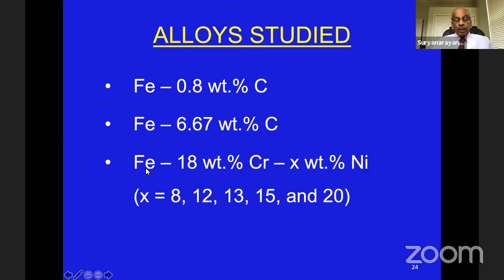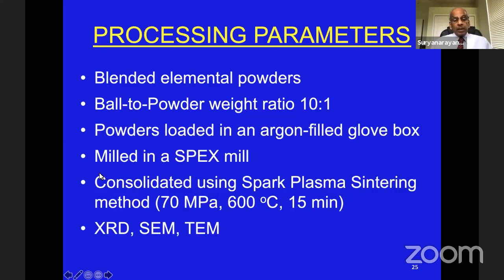And the third one is the austenitic stainless steels, the so-called 18-8 stainless steels, that means iron with 18% chromium and typically 8% nickel. What we wanted to see was what will be the effect of nickel content on the formation of these austenitic stainless steels in this mechanical alloying process. So all these are now developed only during mechanical alloying, and my talk will talk only about mechanical alloying and not the others.